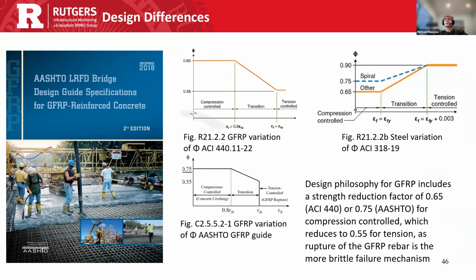So that leads into the design differences for GFRP in general and steel. We looked a little bit in the previous slides at the differences in the behavior, and so now we can better understand why there are differences in the design code. The design philosophy for GFRP is built around a strength reduction factor of 0.65 or 0.75 for the compression controlled failure. With steel reinforcement, that's the more brittle failure mechanism, so it has that larger reduction than ductile failure, but here it's inversed. Compression controlled has a little bit of a warning, a slower process compared to rupture of the tendons or the rebar.